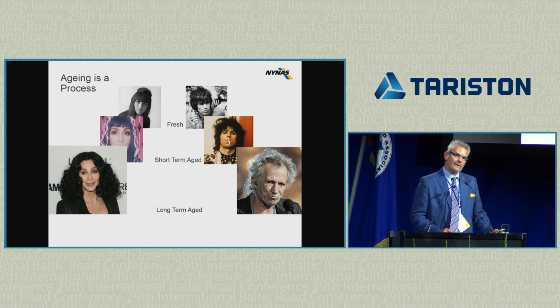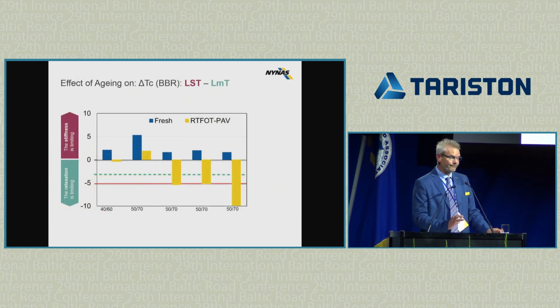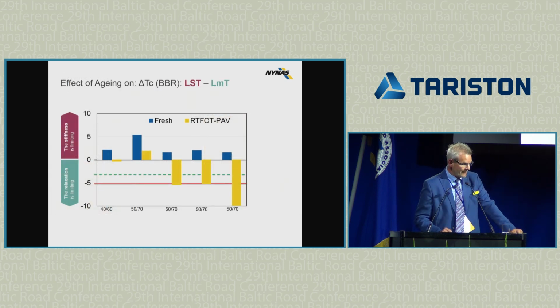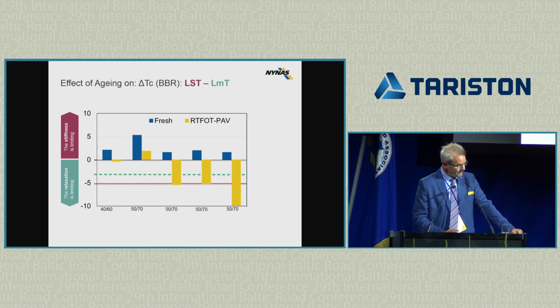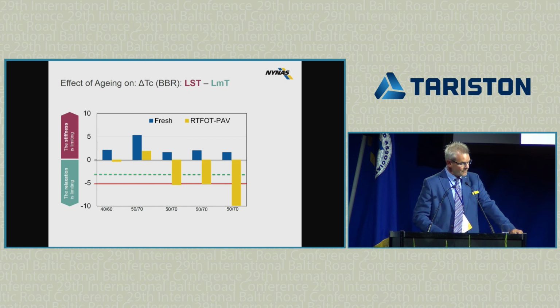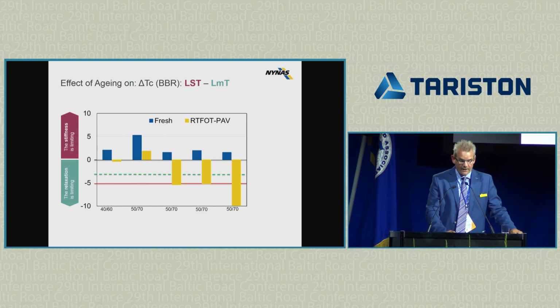So we've looked at a number of standard bitumens in a short-term and long-term aging step. And we've measured delta TC on these 5 different bitumens, A to E. You can see that on the fresh bitumen, delta TC is positive. It's roughly the same. Some are a little bit better than the others. But generally, you can see there's not much difference between these materials. But on the yellow bar, this is after short-term aging and long-term aging of the bitumen.